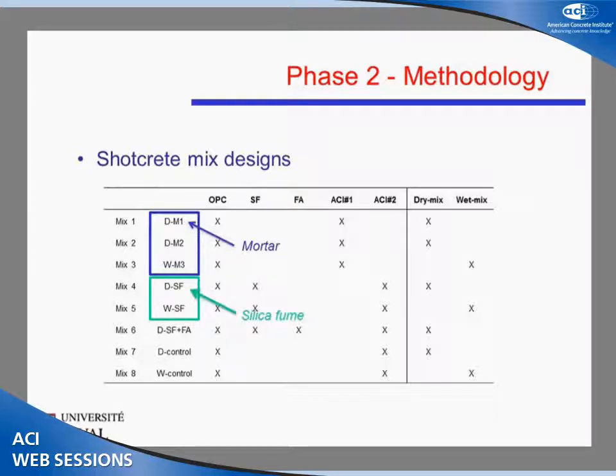The second group of mixes is silica fume shotcrete with coarse aggregate, both dry and wet mix. These are common in East Coast Canada and the Northeast United States. The third mix to be considered is a ternary binder, where the binding agents are OPC, silica fume, and fly ash. This is usually more found on the West Coast and Vancouver. This is actually where the mix is from, Alberta, Vancouver. The control mixes, because you've got to have control mixes: we have a dry mix and a wet mix, again with the same aggregate grading, just to have an idea.